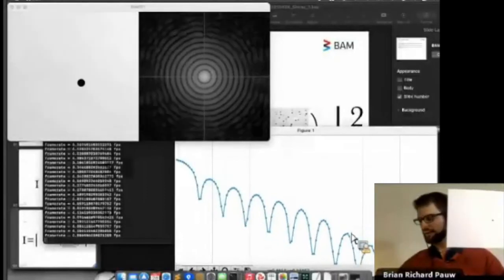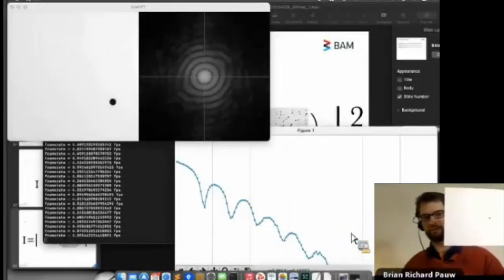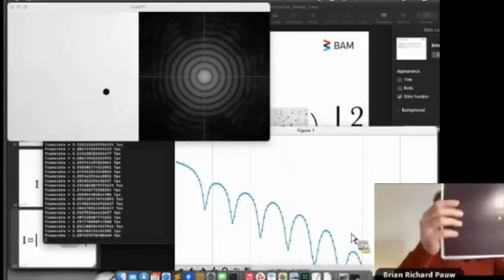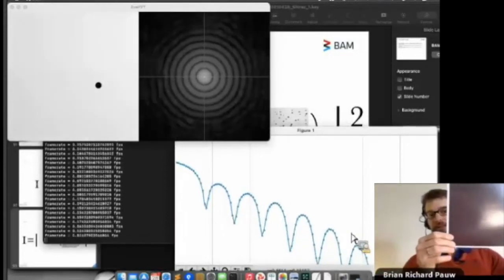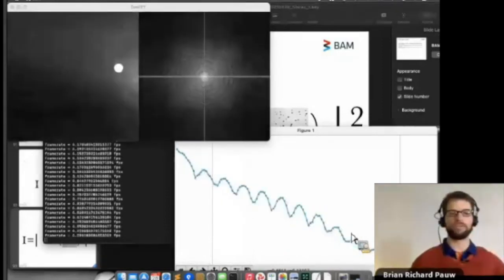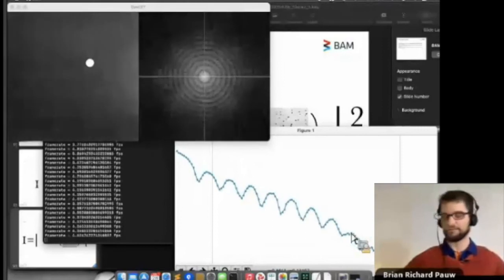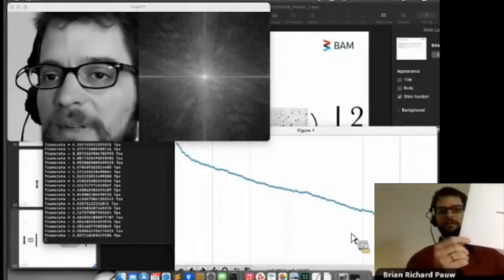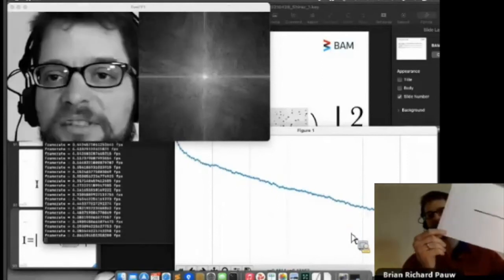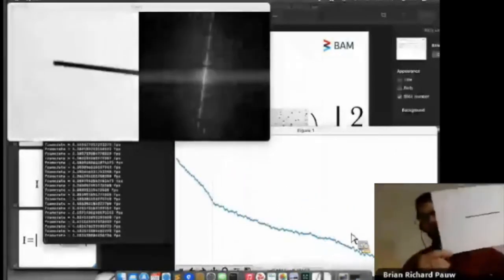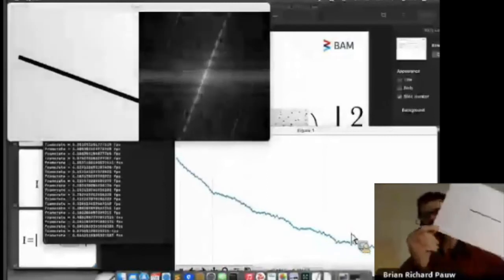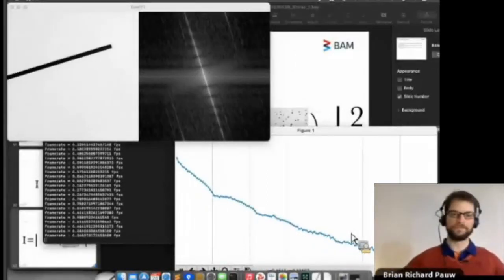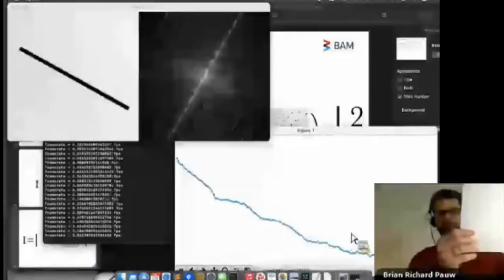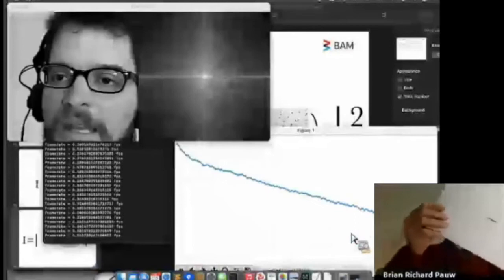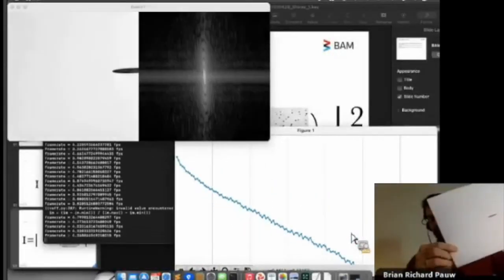Now, due to that information loss that we have, we actually cannot tell the difference between a black sphere on a white background or a white sphere on a black background. Both scatter exactly the same. So this is why you need to input information to get information out. For elongated objects, you get an elongated scattering pattern, and this rotates together with the object. And this is the only thing that makes sense in Fourier space is the rotations, because they stay the same. So you can have things like cylinders or ellipsoids, and these all change together with the object.